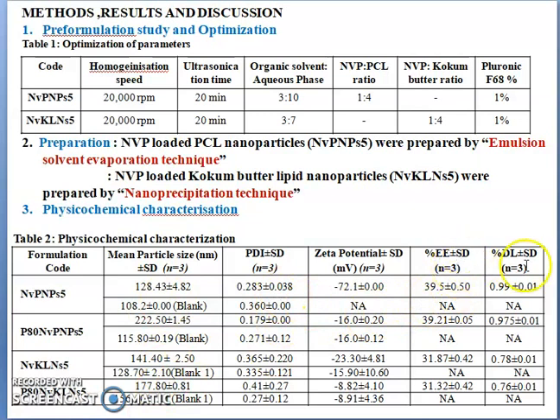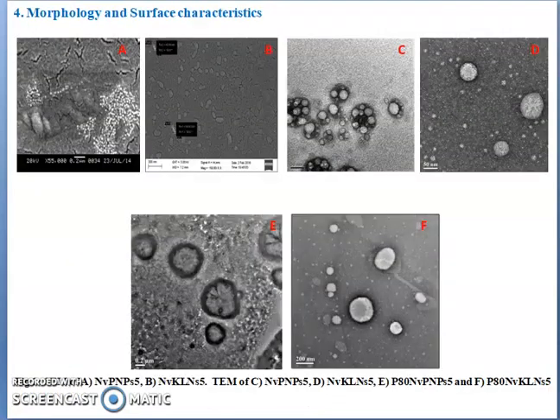Now, if you see the entrapment and drug loading, there is no significant change after coating, which shows that the drug remains intact. Then the zeta potential, there is a reduction in zeta potential. This is for polymeric, it was minus 72. After coating with PS80, it is minus 16. Then this is lipid, minus 23. After coating, minus 8 points. So the reduction in negativity shows that the drug can easily cross the blood-brain barrier, because the blood-brain barrier is